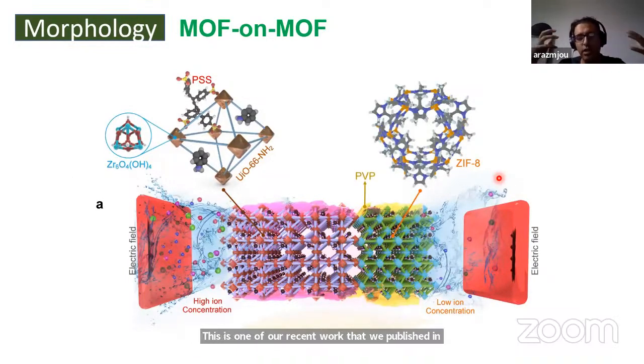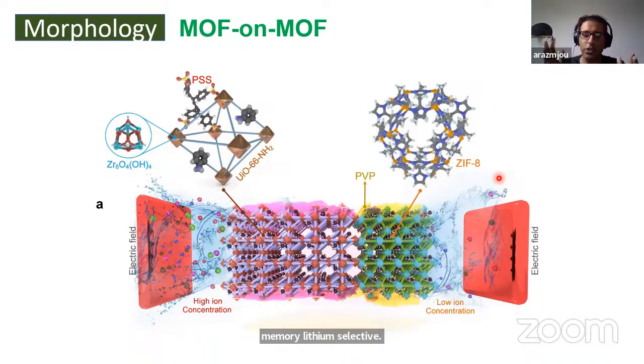So up to here, we realized that if we want to get a lithium selective membrane, we have to alter the chemistry and morphology at the same time. What does chemistry mean? We need to induce asymmetry in chemistry by altering the functional group, for example, or adding charged guest molecules that can provide either a better pathway or a barrier against the movement of lithium. In terms of morphology, we found that if we create an asymmetrical morphology similar to an hourglass, that sort of asymmetry is very important to induce lithium selectivity.